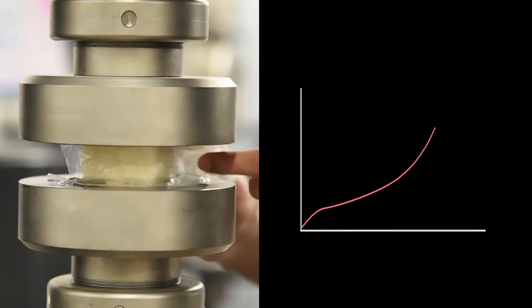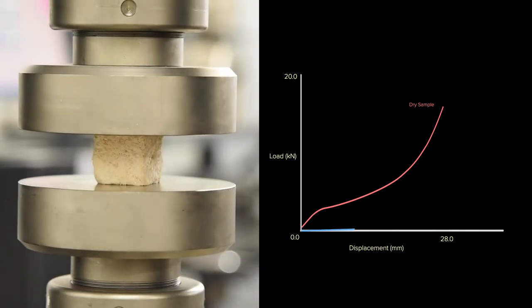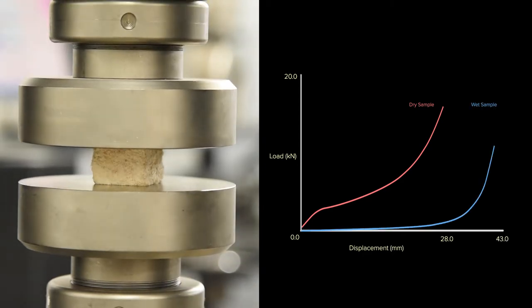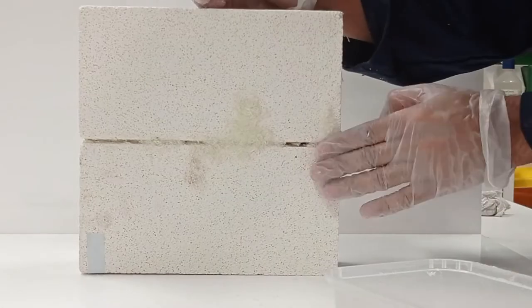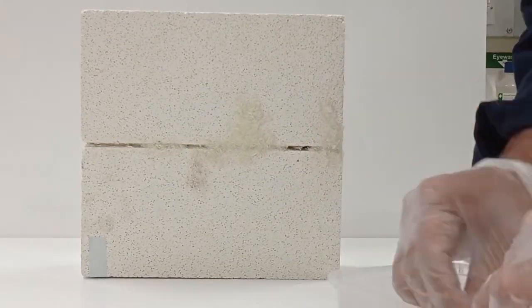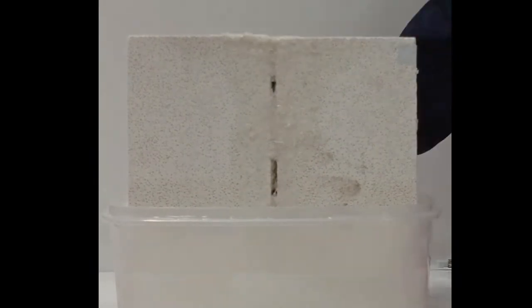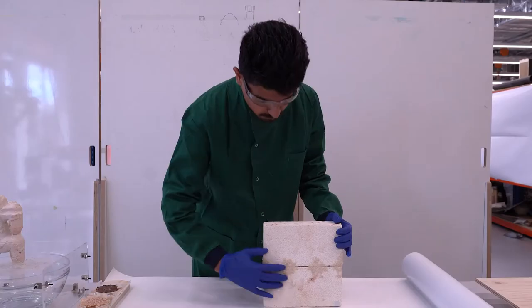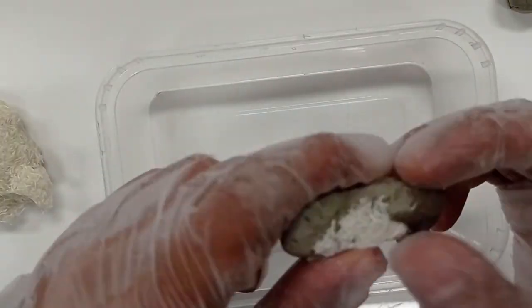The compressive strength of a dehydrated hydrogel composite could nearly match similar to a regular sun-dried brick. The hydrogel composite substrate is used as a mortar to bind bricks together. The cross-linking of hydrogel with plant fiber provides high mechanical strength. And yes, you can pick it up as well.